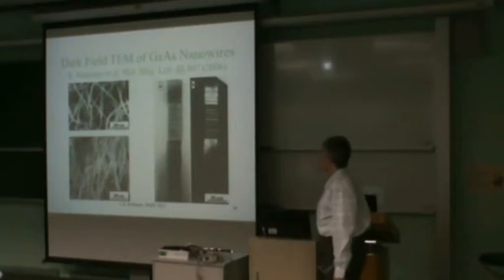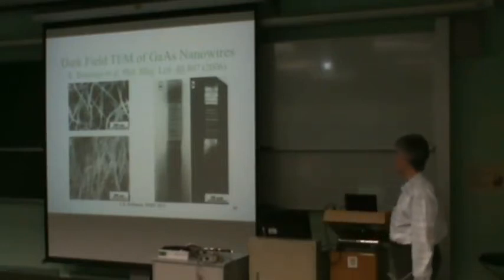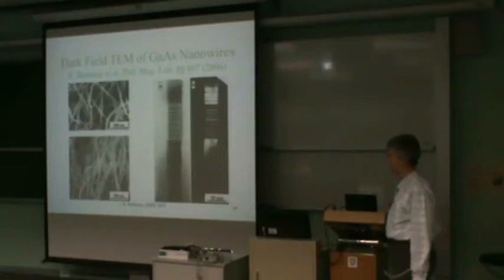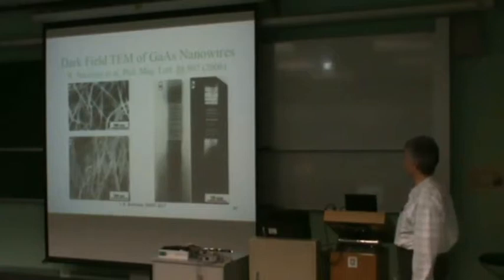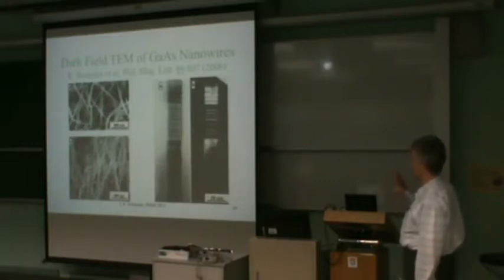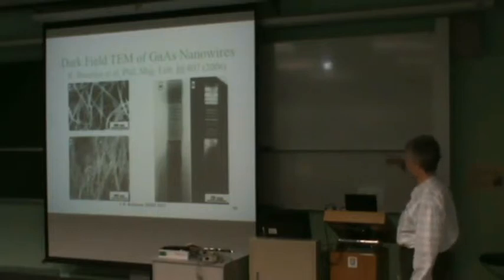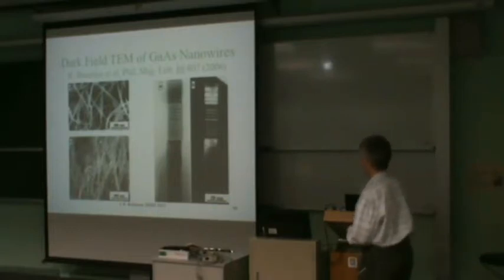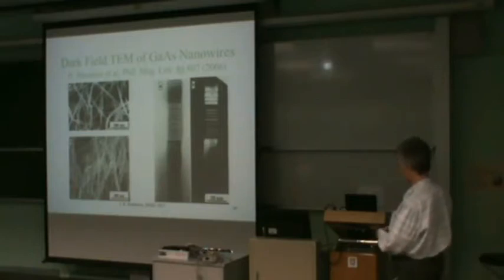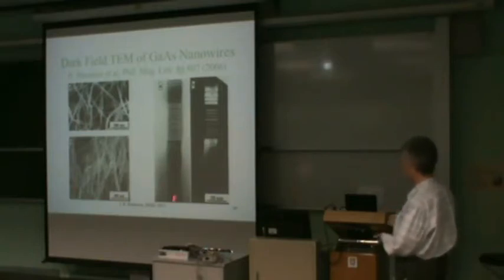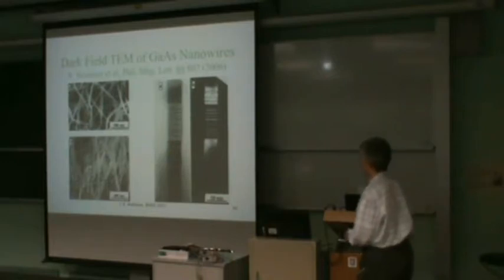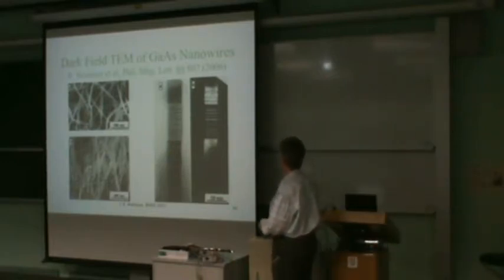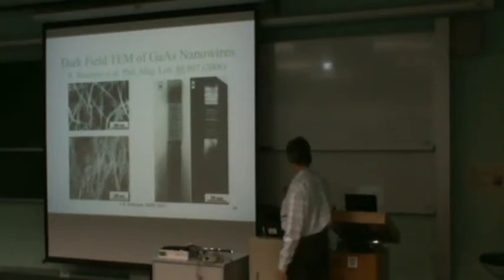Now, as far as the electronic properties, these are quite common in grown nanowires. They're particularly common in indium arsenide, I believe. Gallium arsenide shows them quite strongly. Indium phosphide, as far as I know, does not show them. But these could be controlled if necessary, and so if this was useful for band gap engineering, you could imagine possibly building a technology onto these faulted wires that grow by the VLS method.